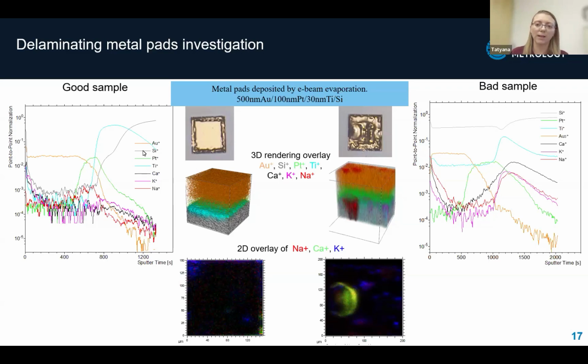The 2D overlays at the bottom tell us even more. In the good sample, we see very little contamination. There are almost no unwanted elements like sodium, calcium, or potassium. But in the bad sample, there is a lot of contamination. Those bright spots on the overlay indicate the presence of these elements.